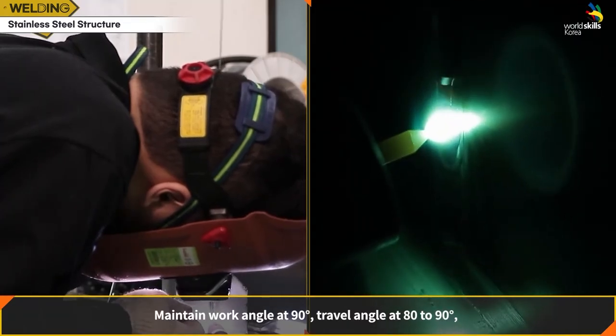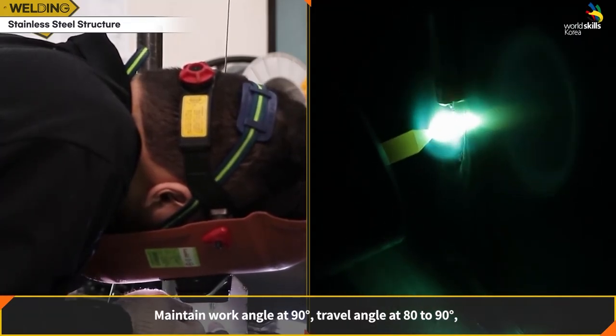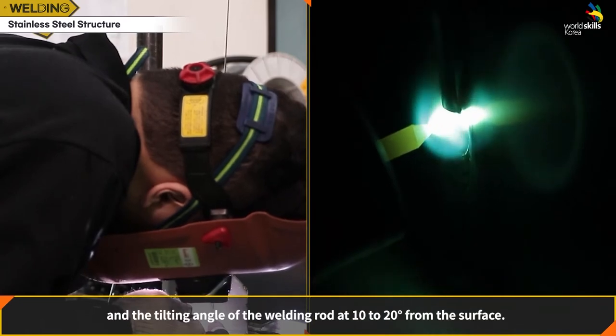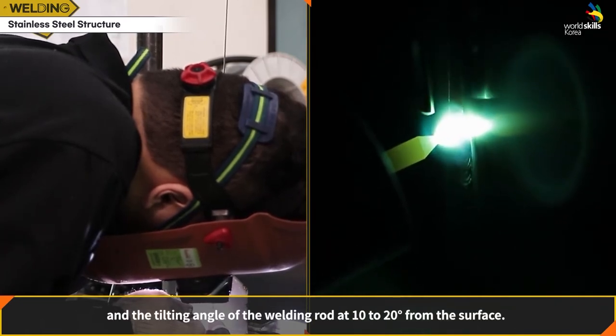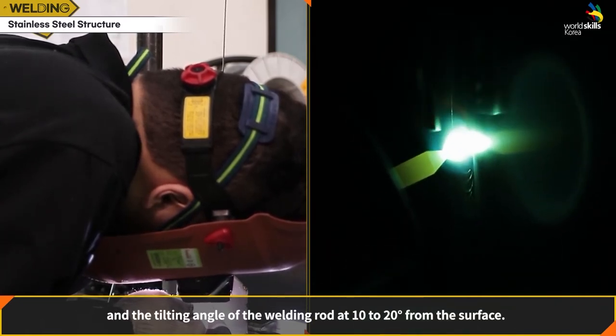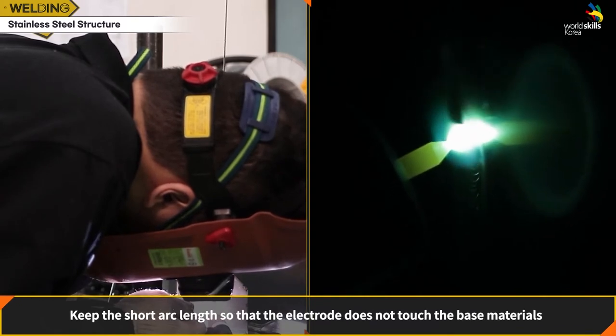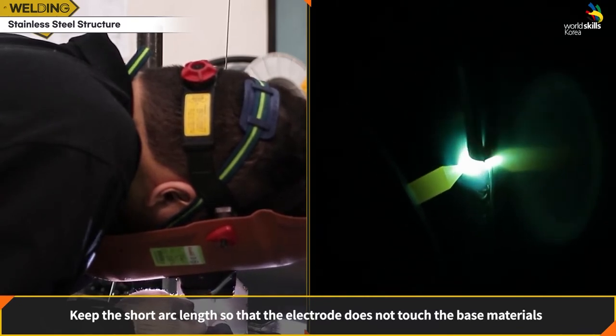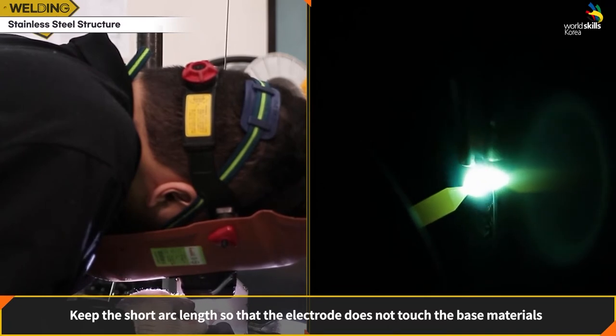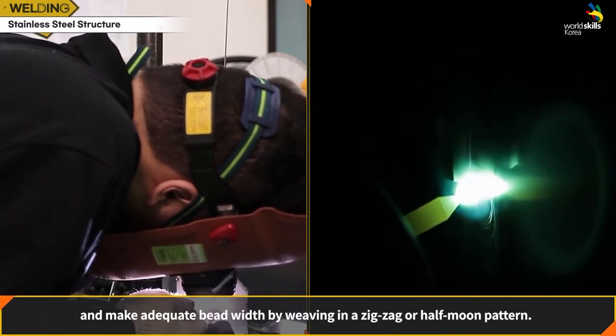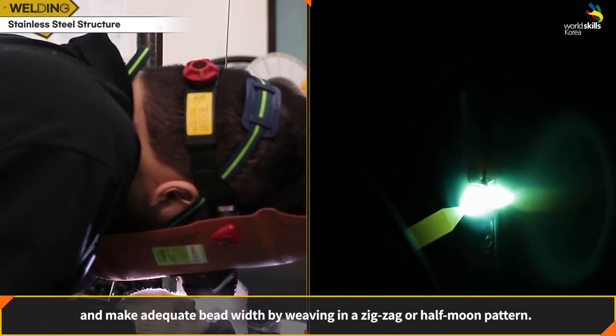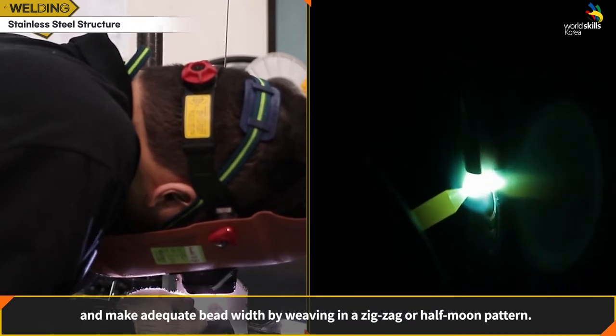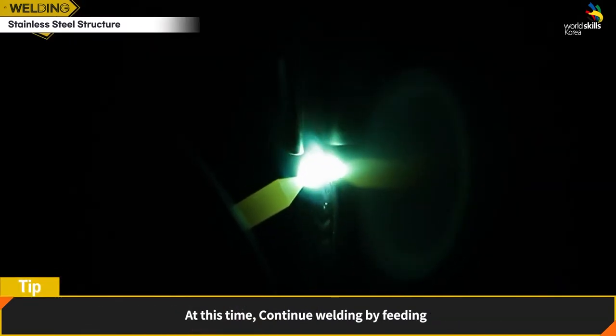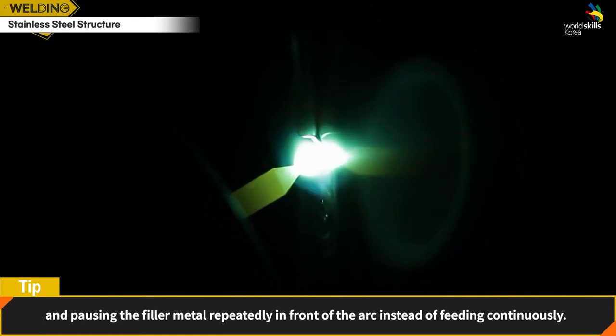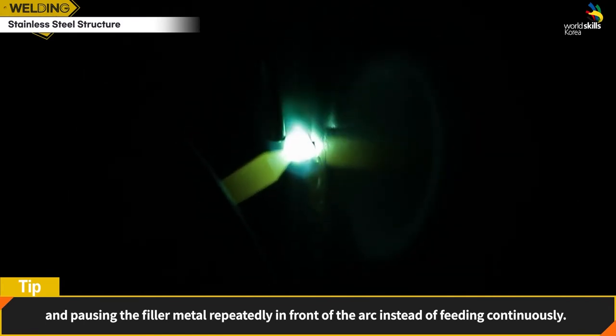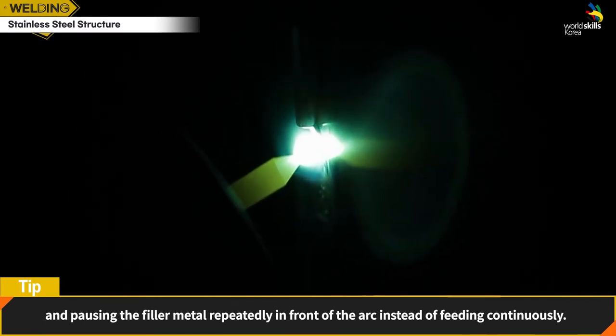Maintain the work angle at 90 degrees, the travel angle at 80 to 90 degrees, and the tilting angle of the welding rod at 10 to 20 degrees from the surface. Keep the short arc length so that the electrode does not touch the base materials, and make adequate bead width by weaving in a zigzag or half-moon pattern. At this time, continue welding by feeding and pausing the filler metal repeatedly in front of the arc instead of feeding continuously.